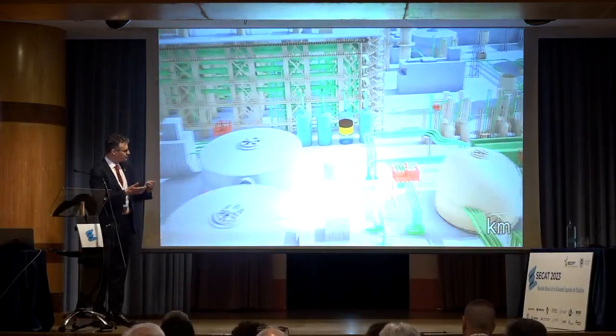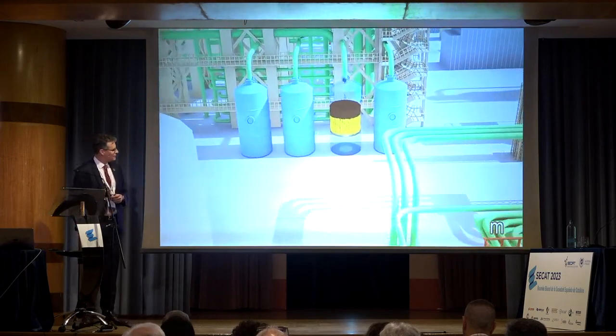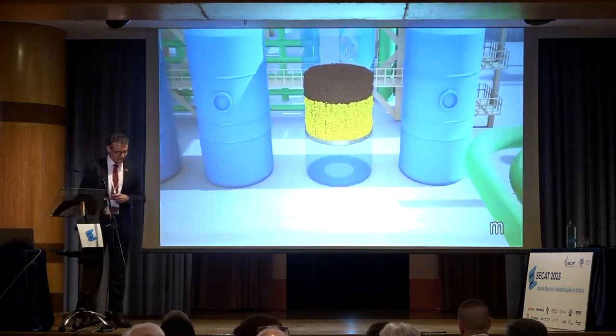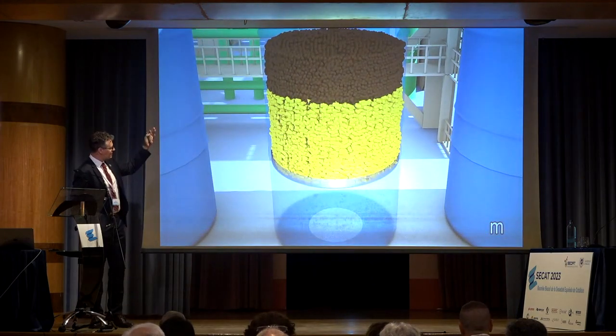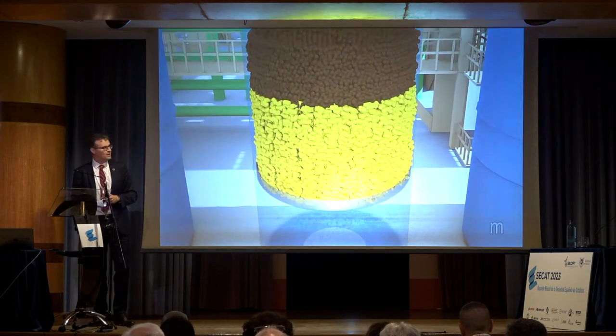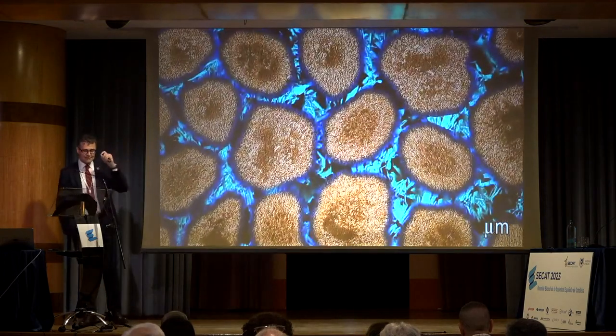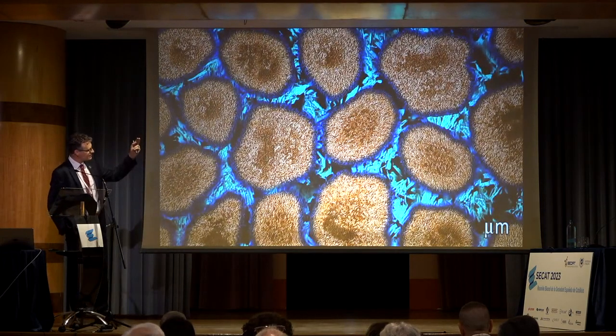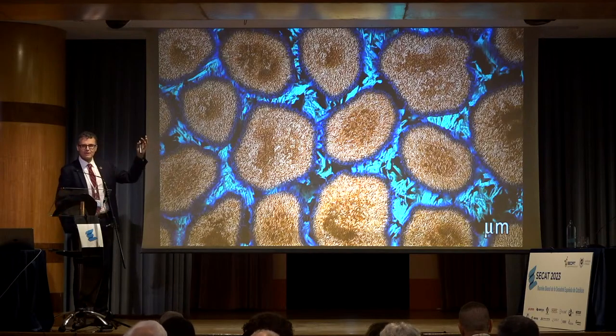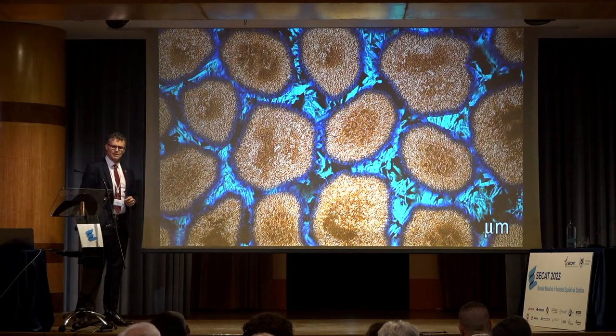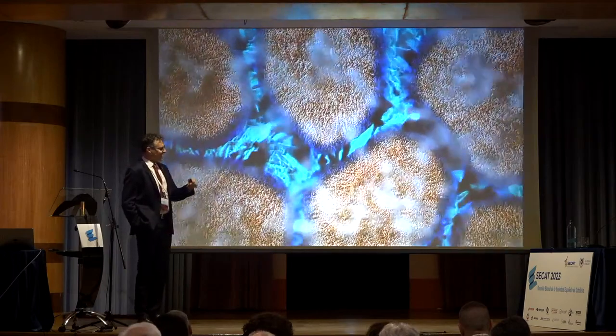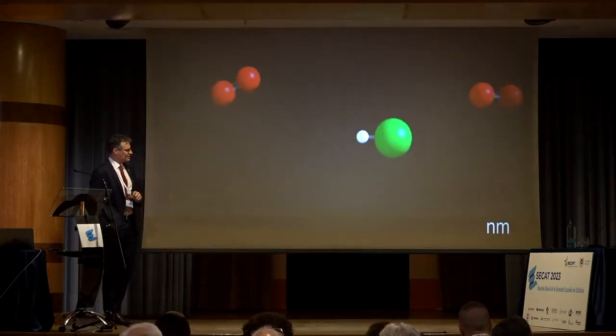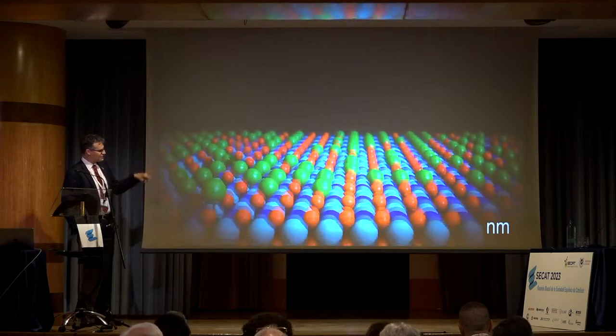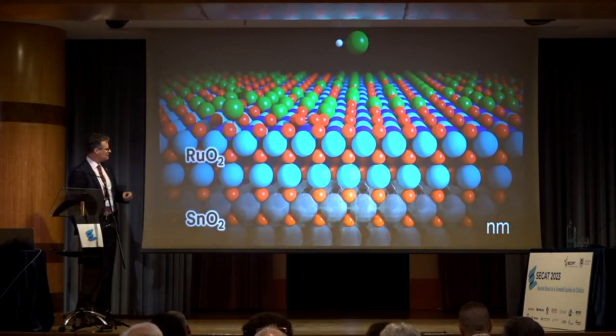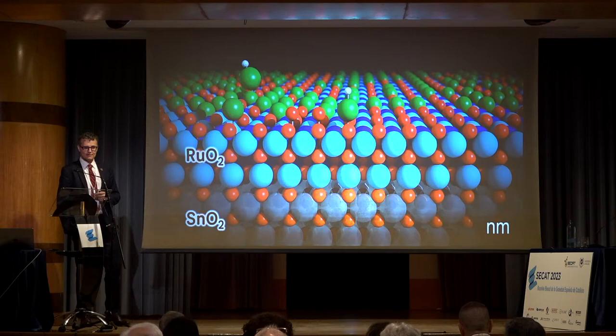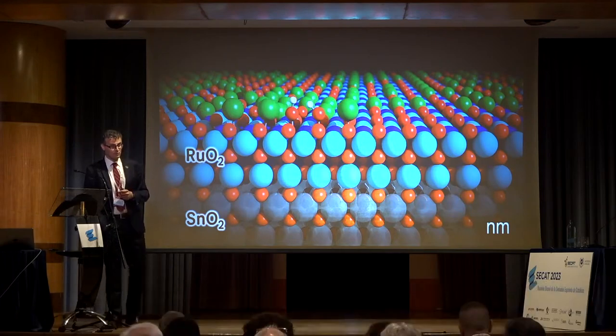And then we go into the reactor where we have the catalytic materials. The catalytic materials, there are 2 catalytic materials. I'm only going to focus on the top one, which is based on ruthenium oxide. Inside these millimeter pellets, you have this nice architecture of carrier, active phase, binders. I will describe them a little bit. We are in the micron range. And then where the engineering starts, it is at the atomic scale, where surfaces of ruthenium oxide, and that's the catalyst that is used, are able to architecture this reaction in a wonderful way.